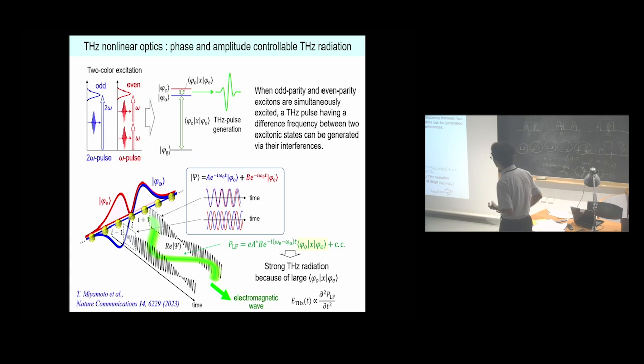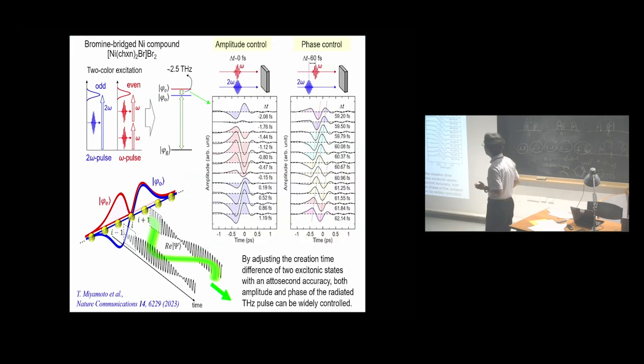so we can expect strong terahertz radiation. This is a demonstration in a 1D Mott insulator, a bromine-bridged nickel compound, which has the largest chi3 among 1D Mott insulators. By adjusting the creation time difference of the two excitonic states with attosecond accuracy, both amplitude and phase of the radiated terahertz pulse can be widely controlled. In this case, only the amplitude is changed, and in this case, with large delta t, the phase of the terahertz pulse can be controlled.